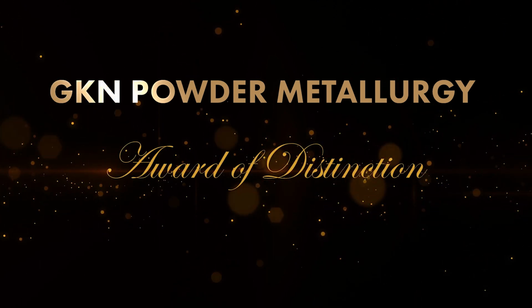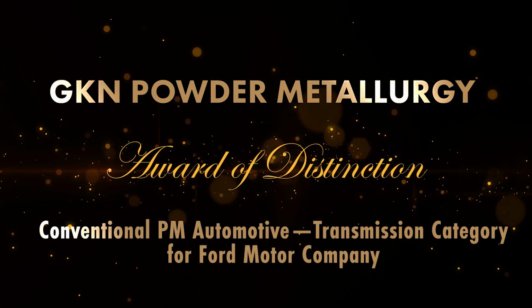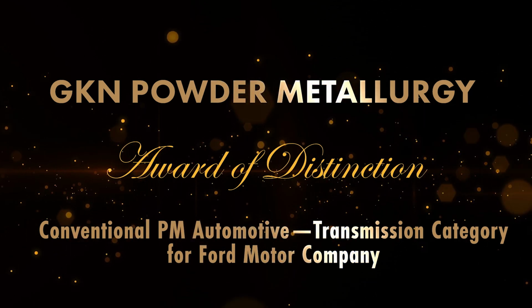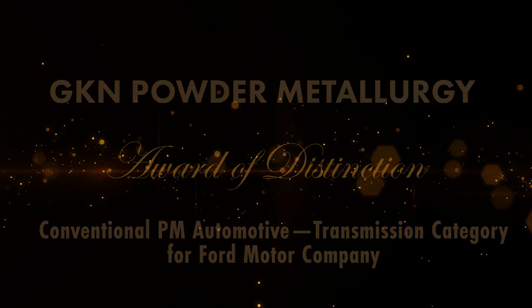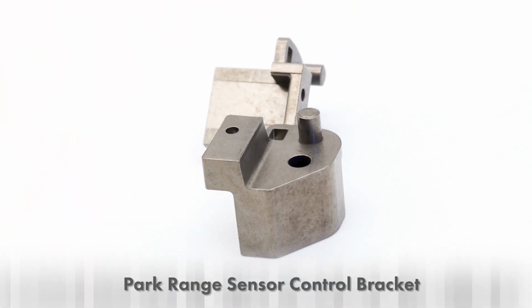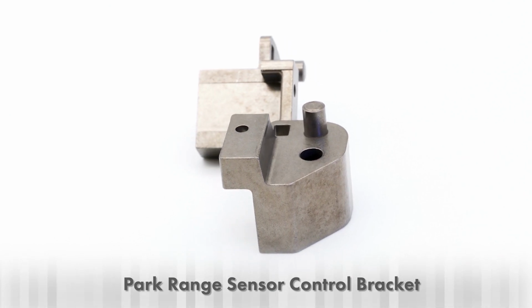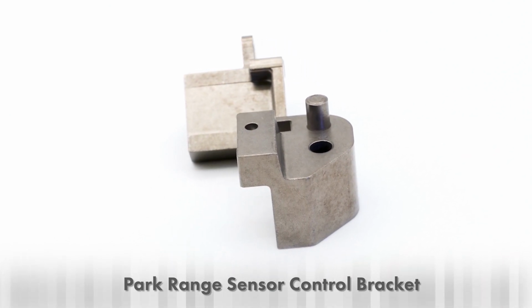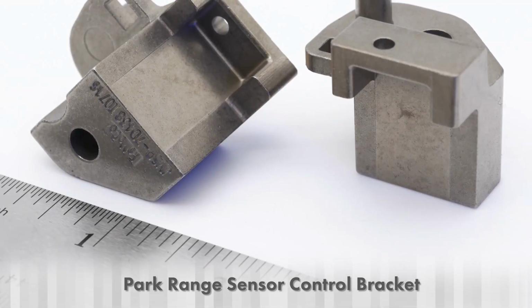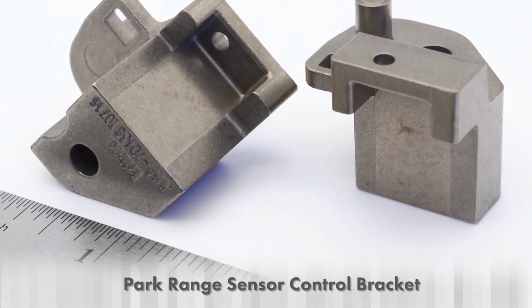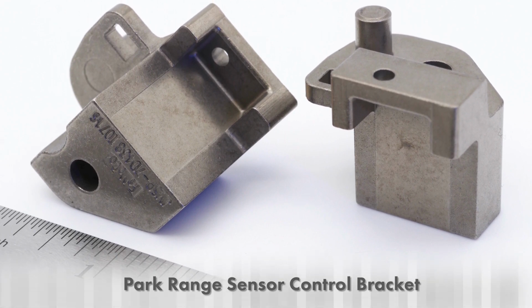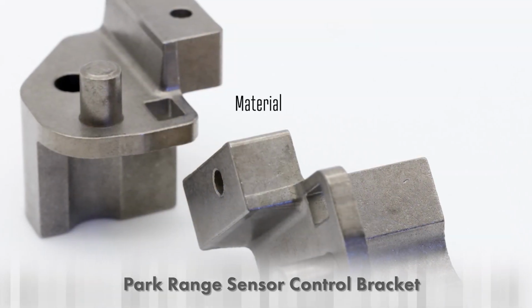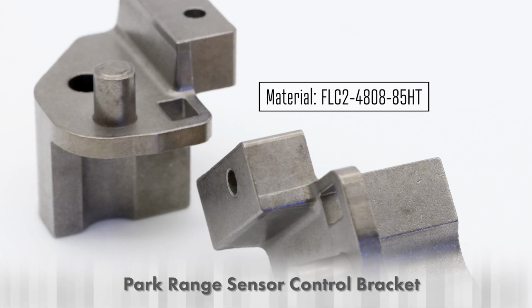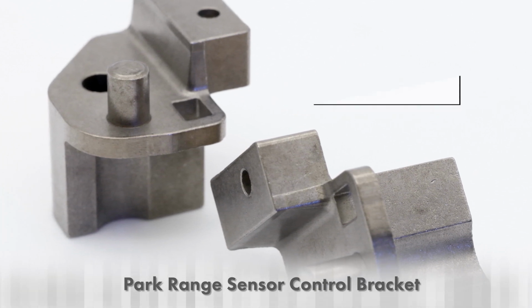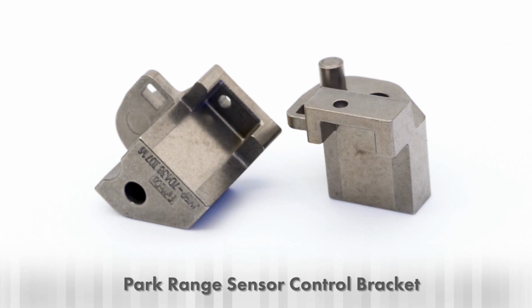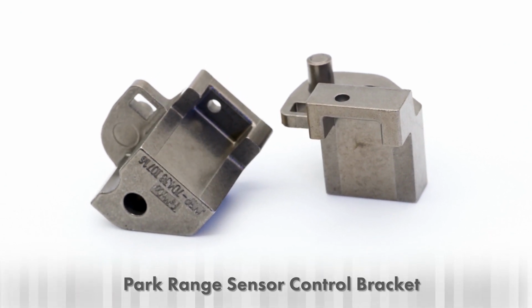GKN Powder Metallurgy has won an award of distinction in the Automotive Transmission category for conventional PM components for customer Ford Motor Company. This award-winning transmission park range sensor control bracket acts as a stop to prevent over-travel of a transmission rod in the parking system. While mechanical properties are not a major concern, the positional tolerance of the part once bolted in place is critical. The part is made from sinter-hardened FLC2-4808-85HT that provides strength and wear resistance and better dimensional control than a quenched and tempered part.